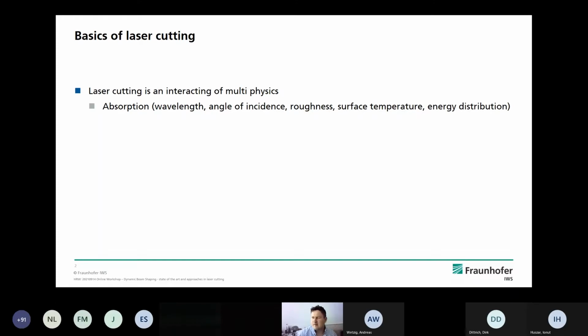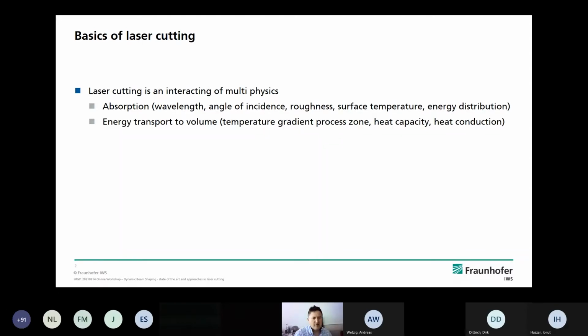So the absorption depth of laser radiation is a few nanometers. That means we also need a kind of energy transport to the volume of the process zone. And also this transport depends on the temperature gradient of the process zone, the heat capacity of the material, and of course also the heat conduction of the material.